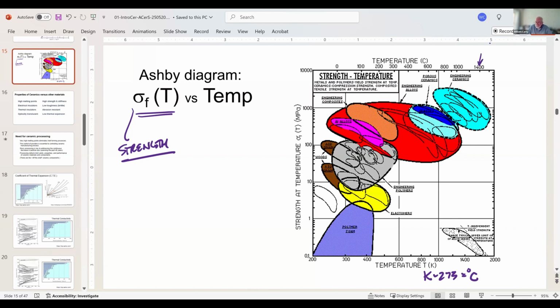What's happened in recent time is we have pushed this out, and we are pushing this out to the 2000 C range. So this eventually is going to come out something like this, and probably something more like this, where our strengths will suffer with increasing temperature because things start to move. Our engineered ceramics, though, have the best high temperature performance of any of the materials, which is great because high temperature applications are what we wish to use them for. Metals, depending on the aluminum alloys, have very limited temperature ability. You're down below roughly 500 degrees C. I can't exceed 500 degrees C.